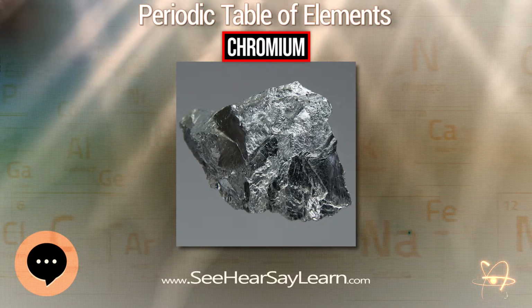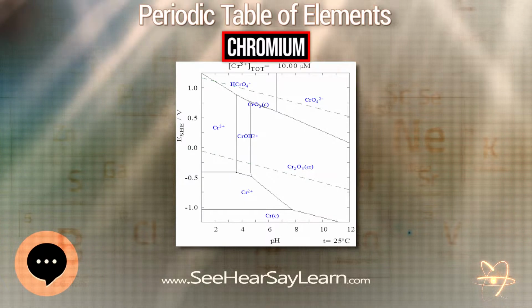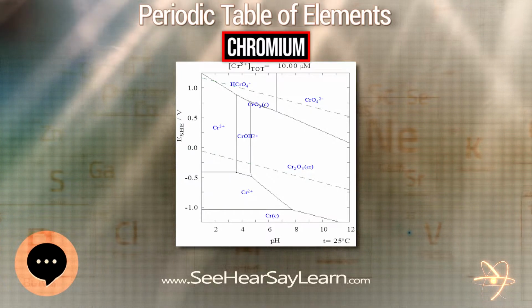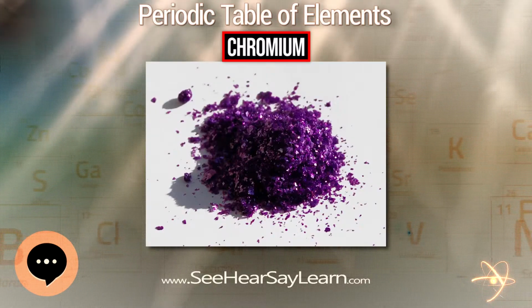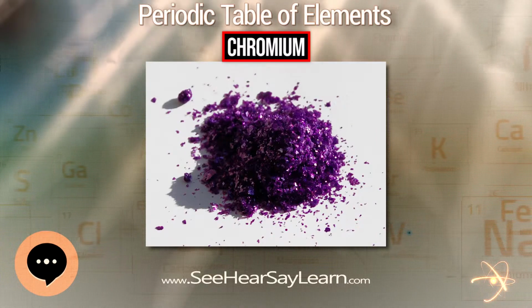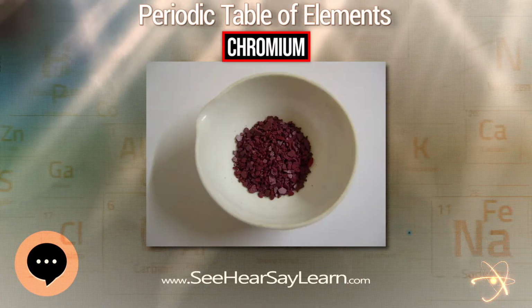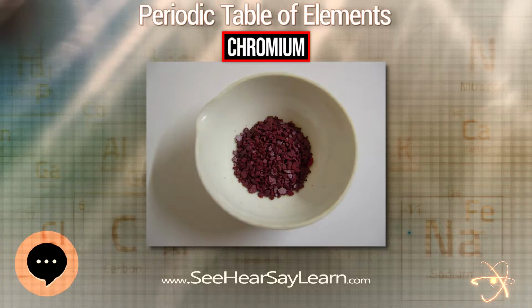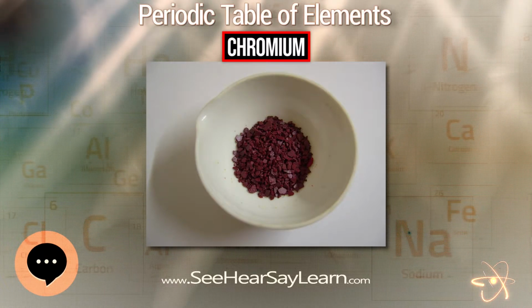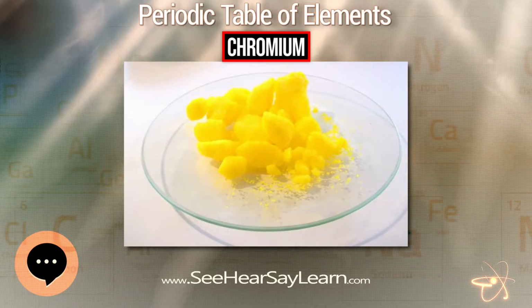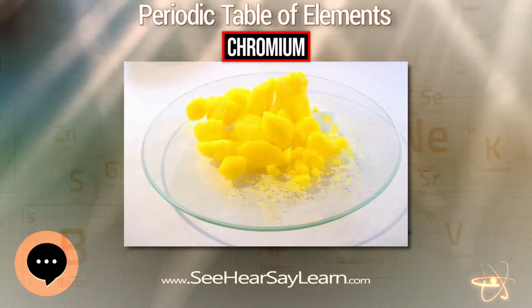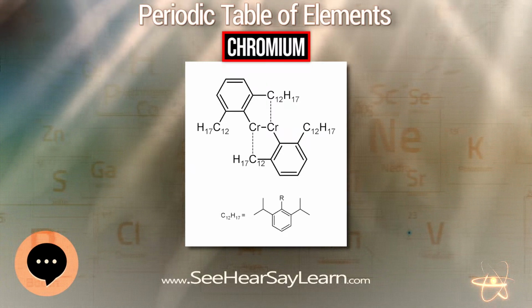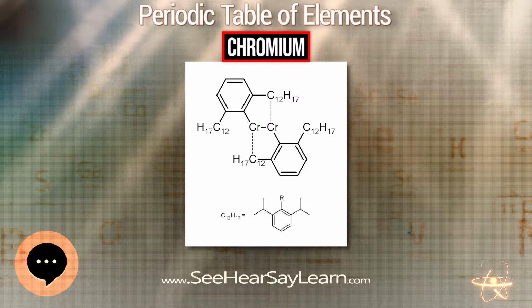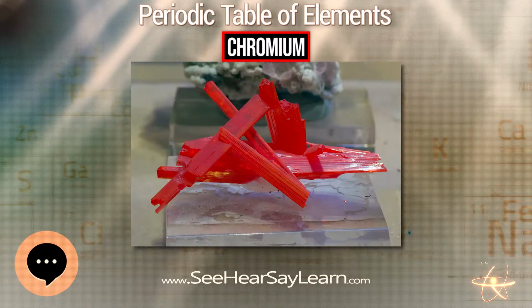For the production of pure chromium, the iron must be separated from the chromium in a two-step roasting and leaching process. The chromite ore is heated with a mixture of calcium carbonate and sodium carbonate in the presence of air. The chromium is oxidized to the hexavalent form, while the iron forms the stable Fe2O3. The subsequent leaching at higher elevated temperatures dissolves the chromates and leaves the insoluble iron oxide.